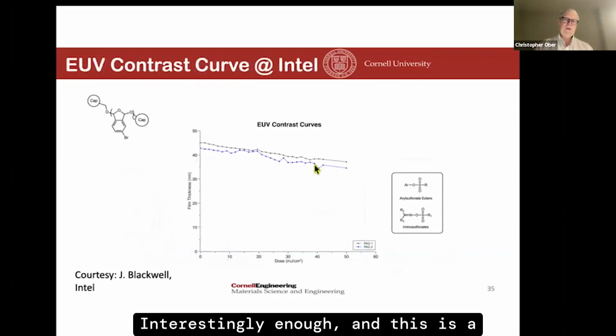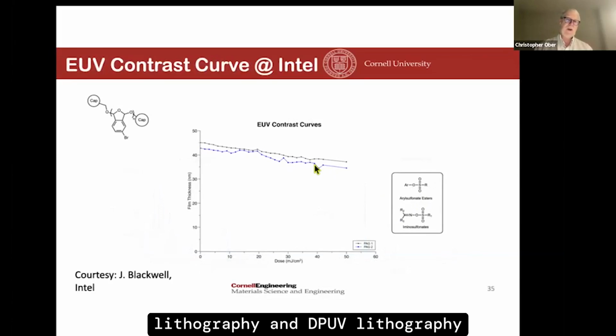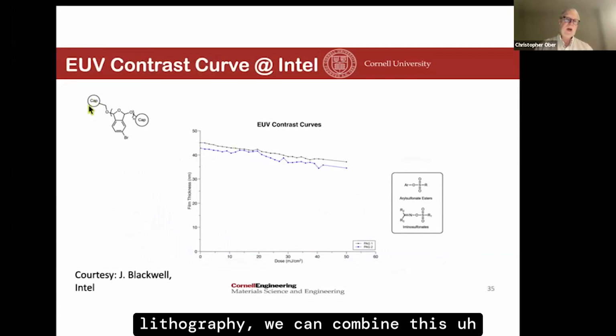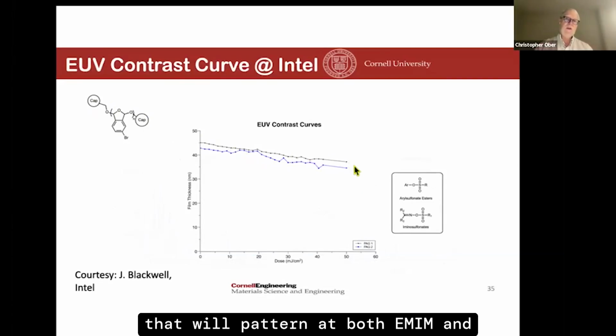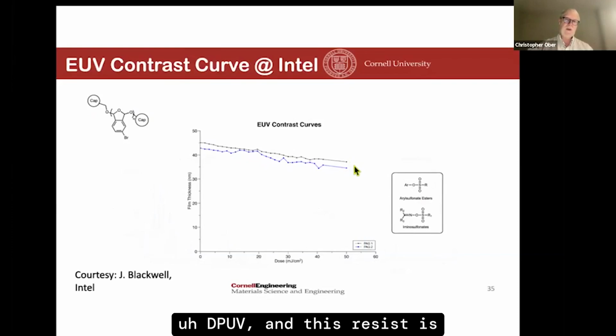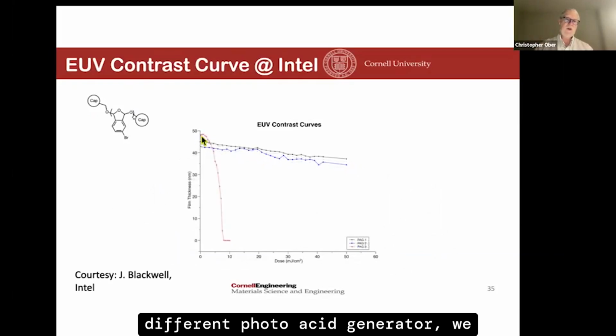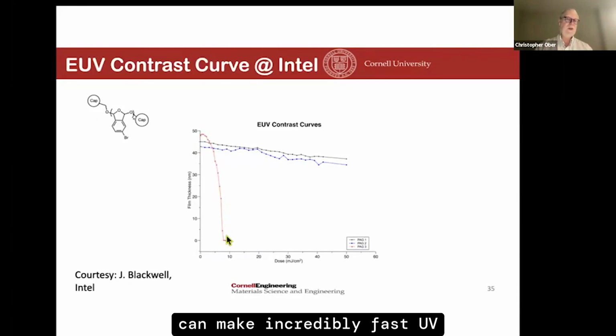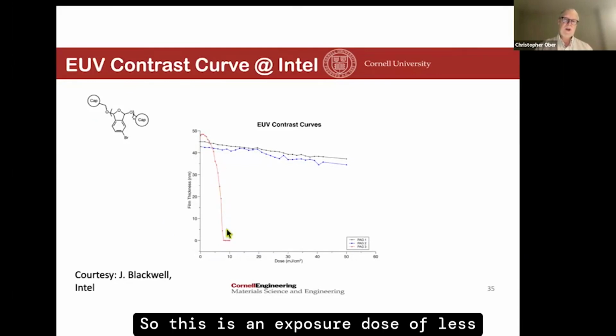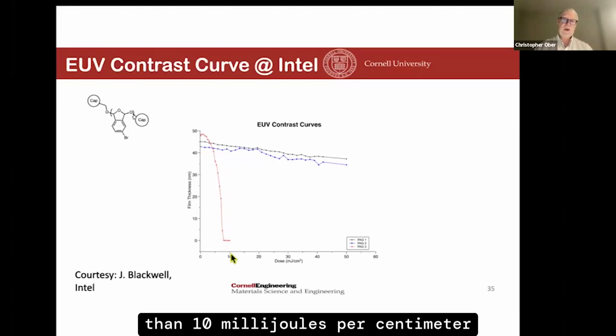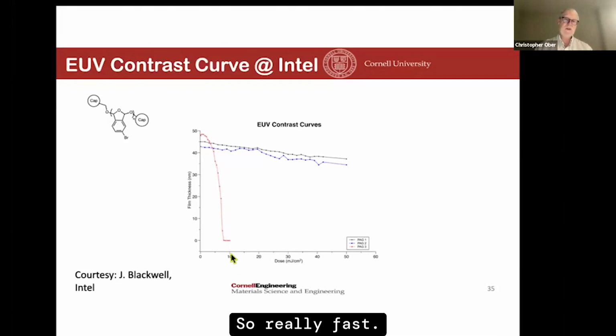Interestingly enough, and this is a key contrast between E-beam lithography and deep UV lithography versus extreme ultraviolet lithography, we can combine this polymer with a photoacid generator that will pattern at both E-beam and deep UV, and this resist is completely dead at EUV. But if we choose a structurally different photoacid generator, we can make incredibly fast EUV resists. So this is an exposure dose of less than 10 millijoules per centimeter squared, so really fast.